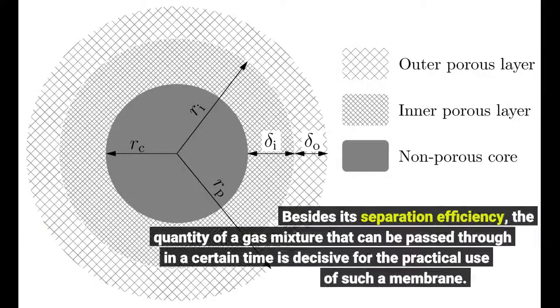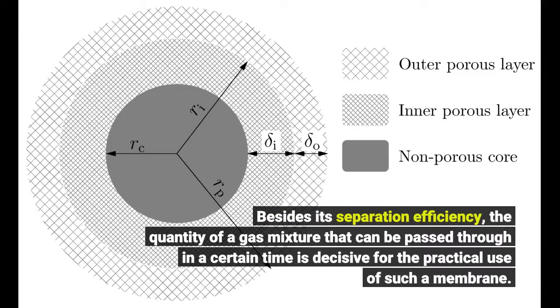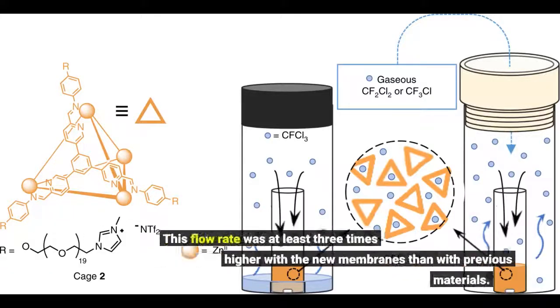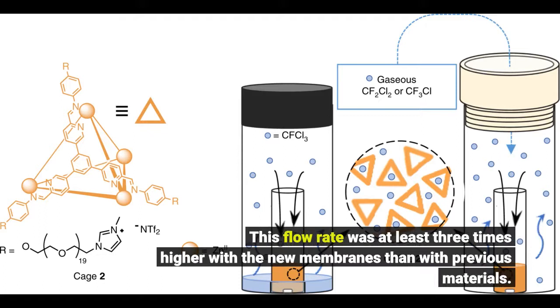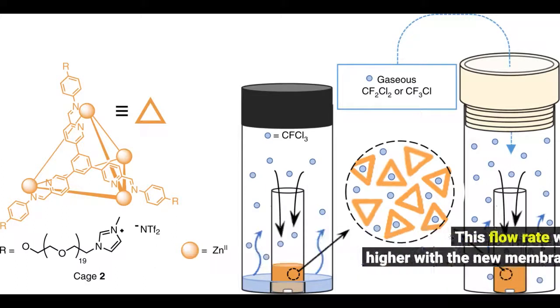Besides its separation efficiency, the quantity of a gas mixture that can be passed through in a certain time is decisive for the practical use of such a membrane. This flow rate was at least 3 times higher with the new membranes than with previous materials. With the separation values achieved, Knebel is convinced that it would pay off for the petrochemical industry for the first time to use membranes instead of conventional distillation processes for gas separation.